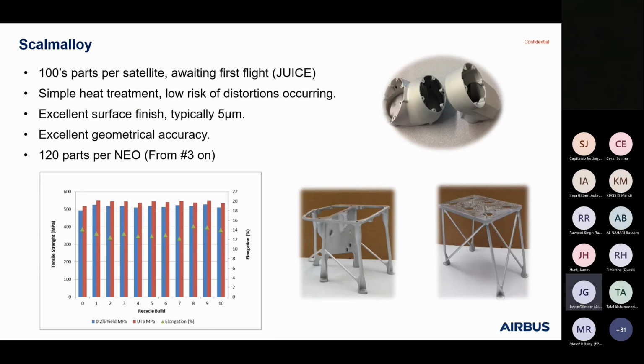So Scalmalloy, where are we now? Qualification took place in 2019 via APWorks. We saw an absolutely superb surface finish, typically 5 microns, so very, very good indeed. The chart on the left, the blue bars represent the yield strength. And what's quite interesting is the batch of parts we made with the lowest yield strength was actually virgin Scalmalloy, which was interesting. We never quite worked that out.